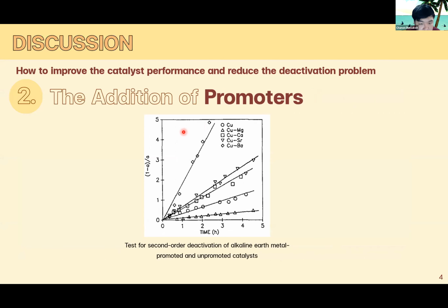And the second alternative is the addition of the promoter. The promoter can help reduce the copper particle size, coke formation inside the catalyst pores, and increase the catalyst stability. And this figure shows the result when we compare the promoted catalyst and unpromoted catalyst. The result shows that when we promote the copper with magnesium, the deactivation rate of the catalyst is the lowest when we compare with the unpromoted. But in contrast, when we use the other promoters, it shows poor performance when we compare with the unpromoted catalyst. The result shows that a suitable promoter can enhance the catalyst stability.